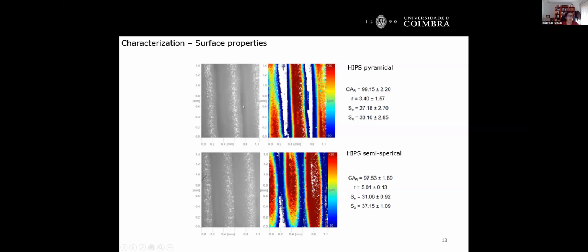Once again, because contact angles are very dependent on the roughness of the surface, and they are very altered, our equipment that measures contact angles also determines the surface roughness exactly at the same point where it's going to measure the contact angle. So you are able to measure the roughness factor, you are able to take the surface roughness parameters, such as in this case the average surface roughness of 27, as you can see very high, 27 and 31 micrometers, and you have a corrected contact angle regarding the surface. And it is demonstrated here for HIPS, both geometries, and as you can see, it's almost the same value. The geometry does not have influence, it's the chemistry that has.